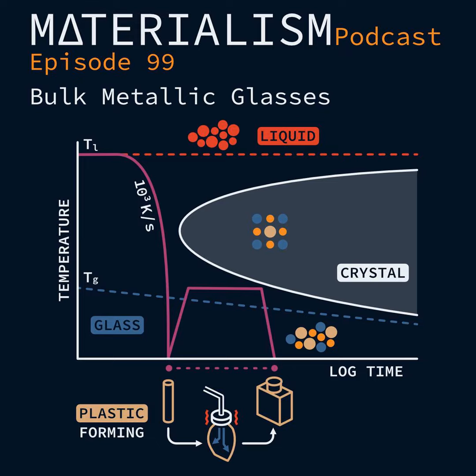My favorite example is a demo that I do for my introductory material science class. It's called the atomic trampoline. Maybe you've seen it, Jan. I'm guessing you have. So it's two metal plates. One of them is regular steel, and one has a couple millimeter thick layer of bulk metallic glass on top. You drop a marble onto both simultaneously inside of a glass tube, so you can see how much they bounce. The one that hits the steel bounces, I don't know, 3-4 times, and it duds out and it's done. And the atomic trampoline goes for, I don't know,